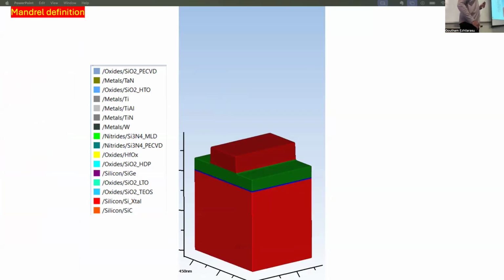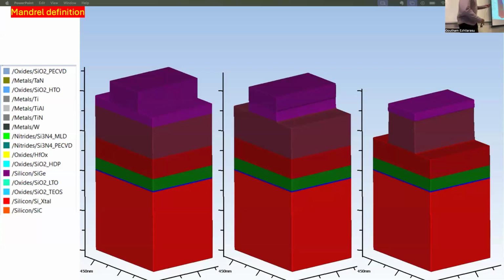Oh, sorry, can you go back one and look at this again? Yeah, I just patterned this, that's all. I just used basically three layers. Transfer it, you're removing the top, and then, no, you're etching first. So first I patterned the Si ARC, then I patterned the planarization layer, then I used this to pattern the poly, right? And patterning is done by dry etching, RIE.